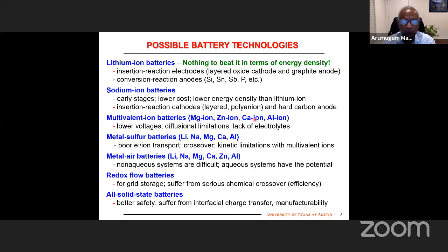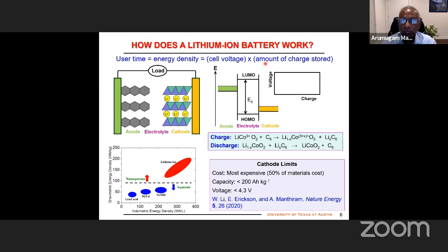Magnesium 2+, zinc 2+, calcium 2+, aluminum 3+. You see, I mentioned to you, the energy density also depends upon the amount of charge stored in the form of ions. If it is lithium or sodium or potassium, if I store one ion, I store only 1 plus charge. If it is calcium, magnesium or zinc, if I store one ion, I store 2 charges, double. If it is aluminum ion, I can store 3 charges. So my energy density suddenly goes up. But when you go from lithium to sodium, the voltage will decrease. Sodium to magnesium or zinc, the voltage will decrease. Yes, you will increase this quantity, but when you go from lithium ion to other things, cell voltage will decrease. So at the end of the day,